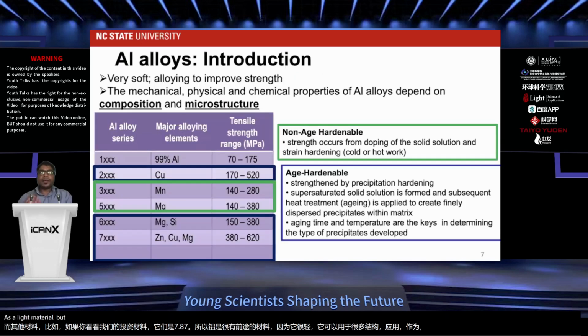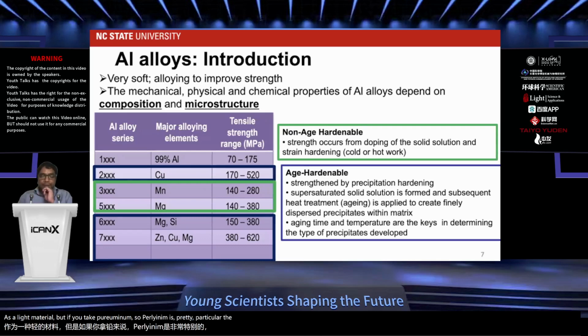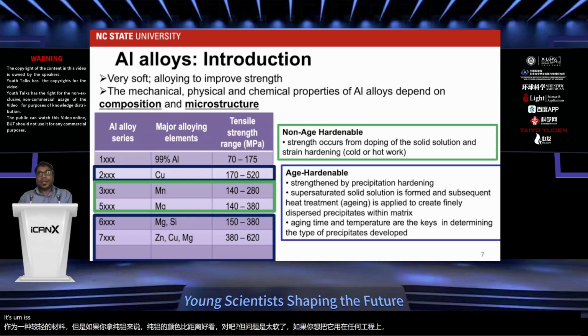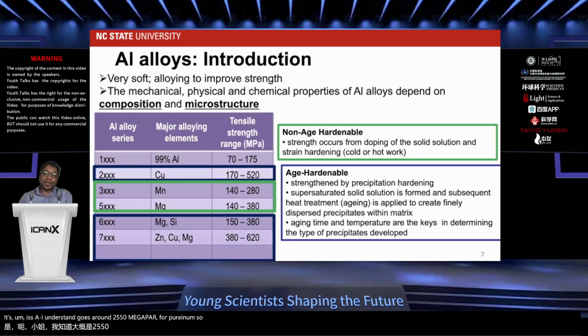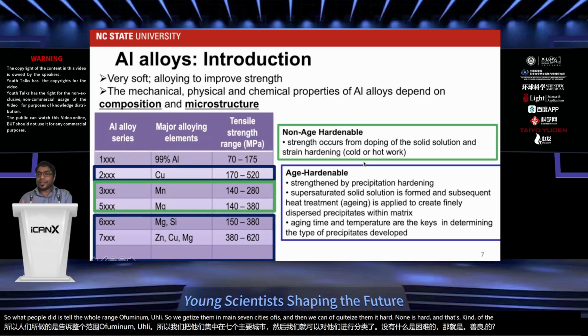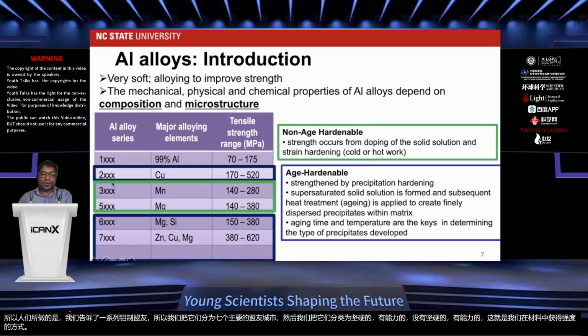But if you take pure aluminum, pure aluminum is pretty corrosion resistant, right? But the problem is that it's very soft. If you want to use it in any engineering application, its yield strength is around 25 to 50 megapascal for pure aluminum. So it becomes not very useful for lots of structural applications. So what people did is develop a whole range of aluminum alloys. We categorize them in main 7 series of alloys. And then we categorize them as age hardenable and non-age hardenable, and that's the way we get the strength in the material.